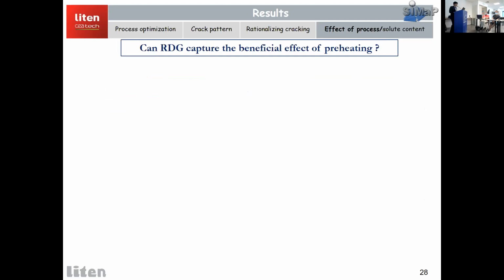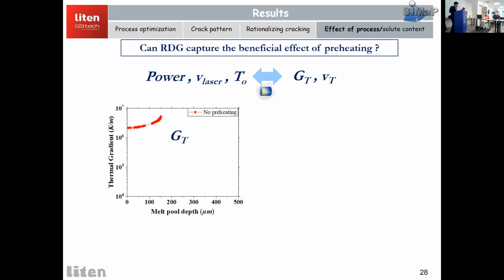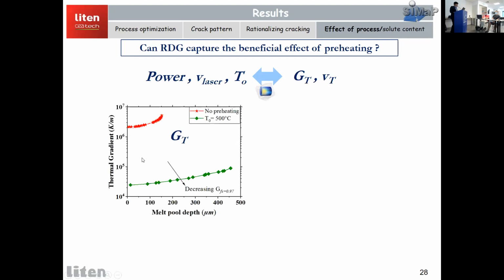So now the idea is, can the RDG model capture the beneficial effect of preheating or not? To do that, we changed laser power, speeds, and the preheating temperatures to have an idea of thermal gradients and solidification velocities. So here is the similar curve, thermal gradient as a function of melt pool for no preheating conditions, the red one. And if we introduce the preheating temperature of 500 degrees Celsius, we see clearly a decrease of several orders of magnitude of our thermal gradients.